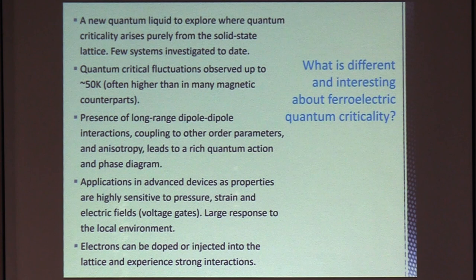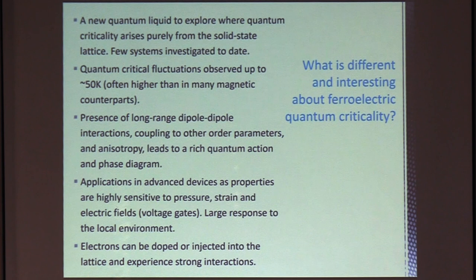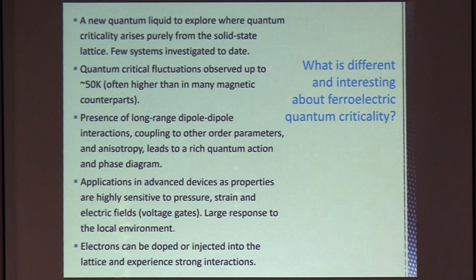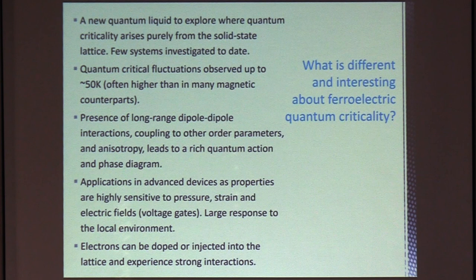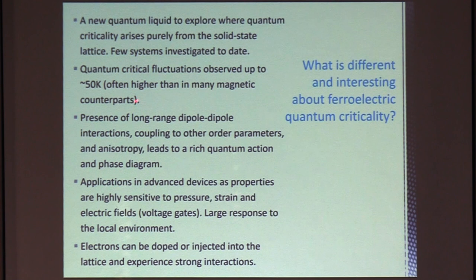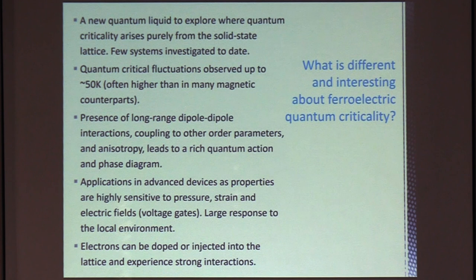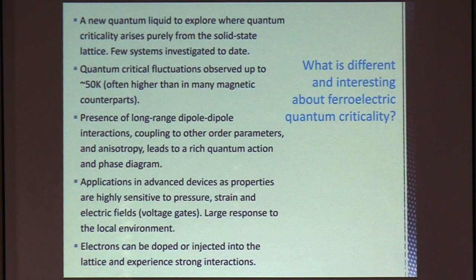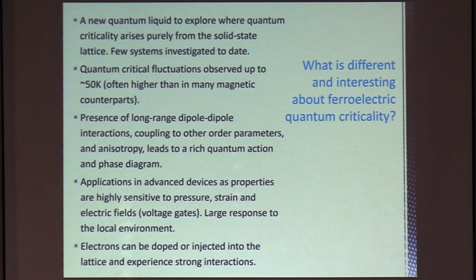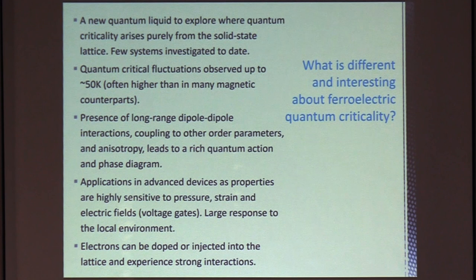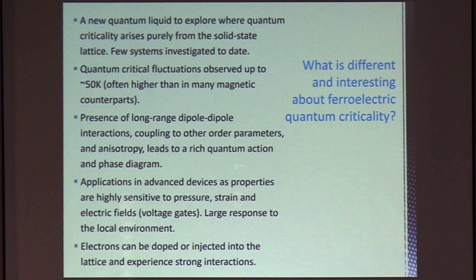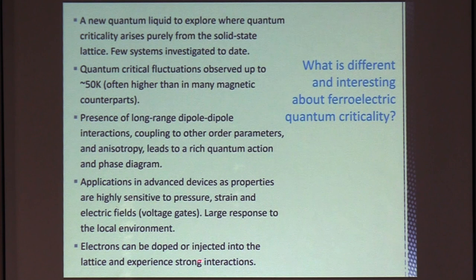So what's different and interesting about ferroelectric quantum criticality? Well, it's a new quantum liquid to explore where quantum criticality arises purely from the solid state lattice, not from the electron system. And there's few systems investigated to date. Quantum critical fluctuations are often observed up to quite high temperatures. In the case of strontium titanate, around 50 Kelvin, which is often quite a bit higher than in many magnetic systems. The presence of long-range dipole-dipole interactions and strong coupling to other order parameters and anisotropy leads to quite a rich quantum action and a rich phase diagram.